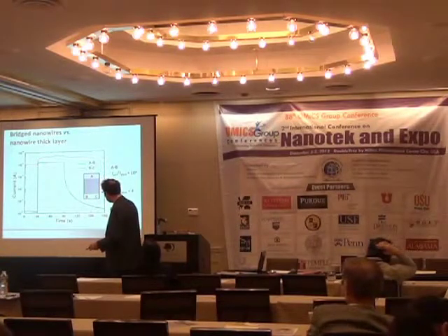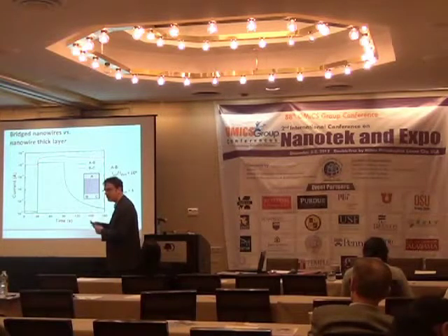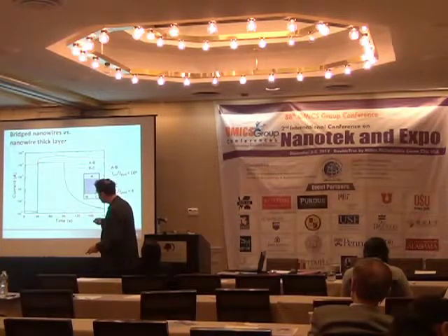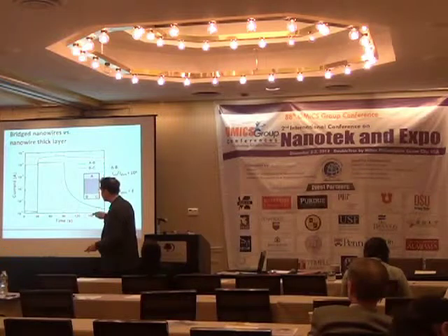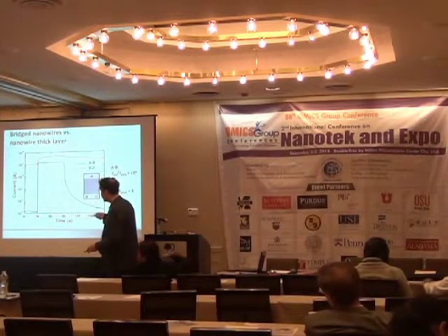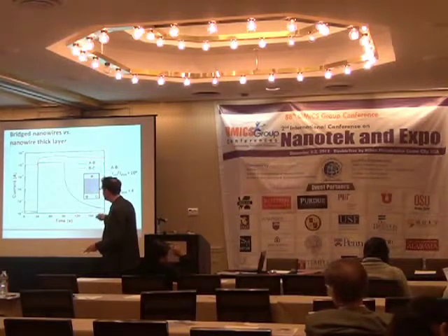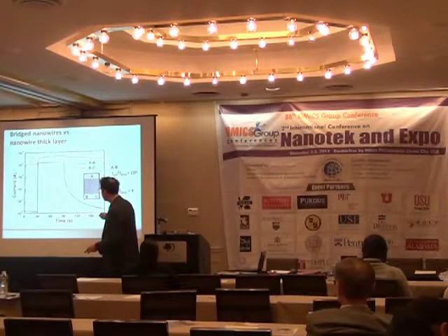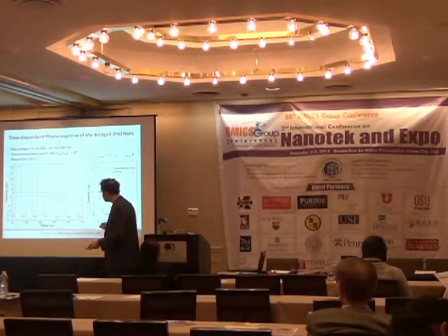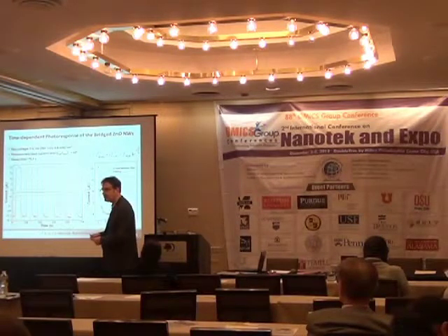Now, if you measure between the points A and B, you have to cross through the bridge, and then you start with a very low dark current, and you get a much more exciting response with 4 orders of magnitude difference. This is a large scale. So this is a large increase, and you have a kind of sluggish decrease in this region that I will try to explain. The slow response is a bit difficult. This is due to kinetics.